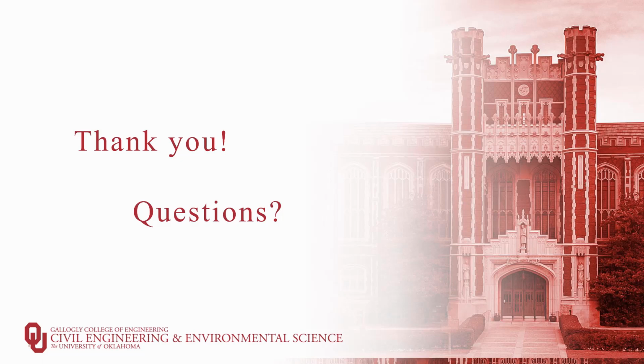So that's a good question, and like we've mentioned a few times, it takes some practice to get the two controlled. We have a very flowable SCC conventional concrete, and the UHPC is also very flowable, and will flow out of any gaps that you can find anywhere. So we went with recommendations from some of the previous work that's been done at OU, at Florida, and elsewhere, of having a divider that helps to set that location and also to provide some separation at the beginning. It's only a portion of the width across the beam, but it gives us the reference point of where we want the interface to be.